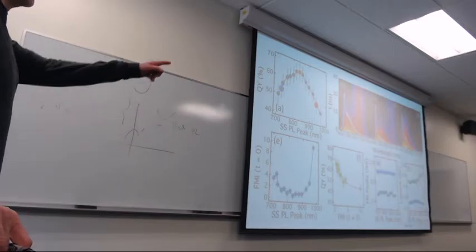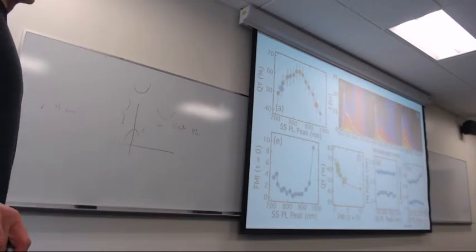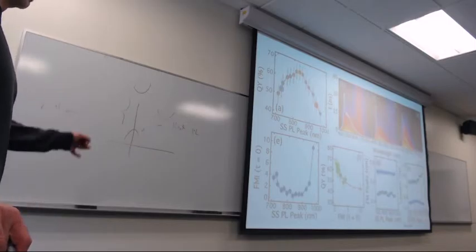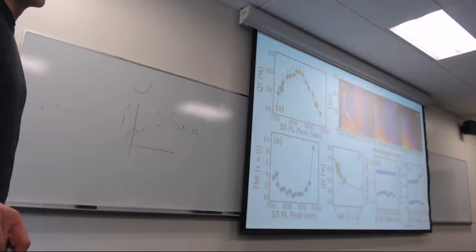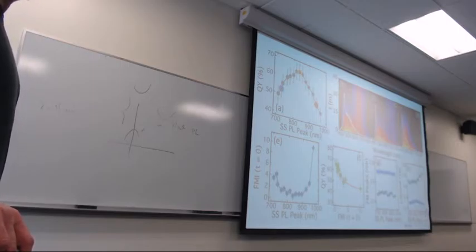The question is, what is this fast decay? It's either surface states or some kind of direct transition. But there was also a lot of discussion about oxygen impurities. There's no oxygen in this problem for silicon. The way we've done this, we've done all the synthesis and size separation and characterization without ever letting them see air. It's been quite a challenge. But there still might be surface states because you cannot completely control the surface. Is it carbons or hydrogens? NREL says it's mixing, but they don't say where it comes from. But they say that they don't have any passivation issues.